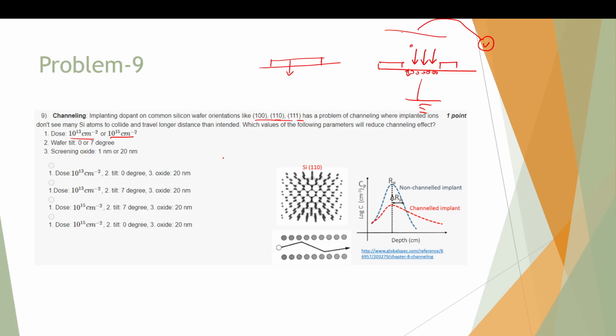So, what will happen in channeling is, if you see the silicon surface, since it is a crystalline solid, there will be atoms arranged in some nice periodic manner. So, there will be such channels which the impurities will see, and they can go through them. You can see in this cartoon, this impurity is going through a channel. Somewhere it will collide, but because there are these open paths, it can avoid a lot of collisions. Because of that, the profile that we expect for a non-channeling case will look something like the blue curve, but for the channeling case it will have a tail at the end. This tail is something that we did not expect from our calculations. So, that is not desirable.